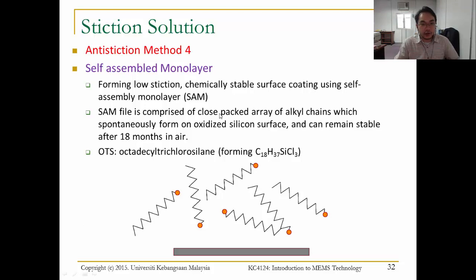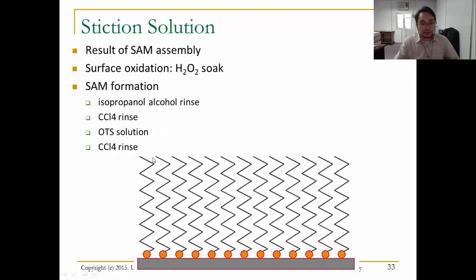A SAM film is comprised of a close packed array of alkyl chains which spontaneously form on an oxidized silicon surface and can remain stable after 18 months in air. Okay, so an example of a SAM is octadecyltrichlorosilane. So the structure of the monolayer involves a methyl group which is sticking out, and this methyl group will prevent two surfaces from sticking to one another. So you can imagine this to be as if it is a non-stick surface.